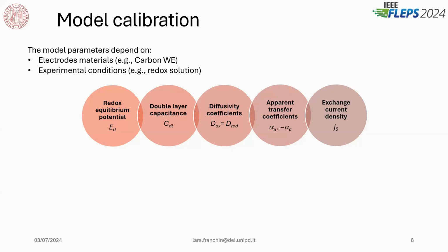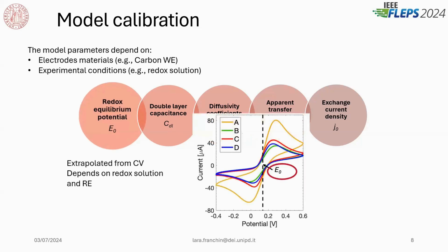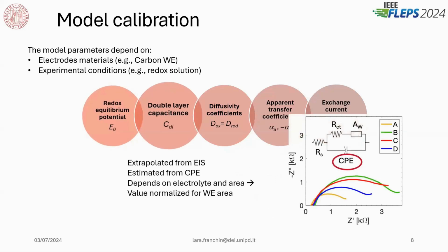In fact, we have identified these 5 parameters that are the main ones of the model. The redox equilibrium potential, which is retrieved by Cyclic Voltammetry curves, and it is dependent on the redox solution and, of course, the reference electrode that we use. The double layer capacitance in this case is extrapolated by fitting a CPE modified Randles circuit on the impedance spectroscopy measurements, and it is estimated from the constant phase element, of course.